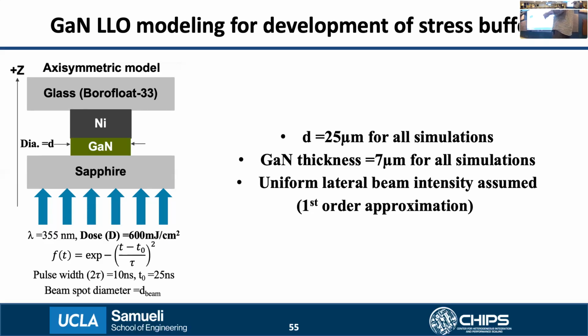There are also some assumptions here: the diameter of the GaN film is around 25 microns for the simulation, and the thickness of the GaN is 7 microns. Even though we use a Gaussian beam spot on the sample, for a first order approximation, we assume that the lateral intensity of the light is uniform, so there is no lateral variation in the light intensity. Any questions about the assumptions here?